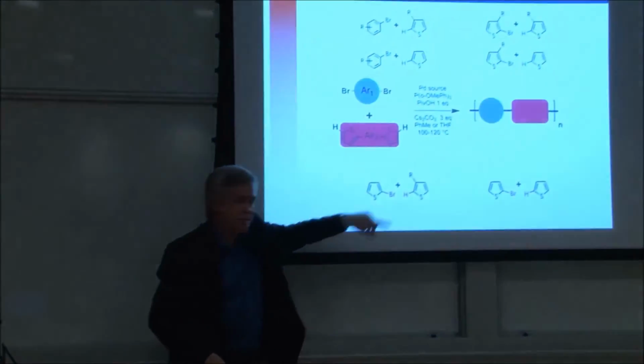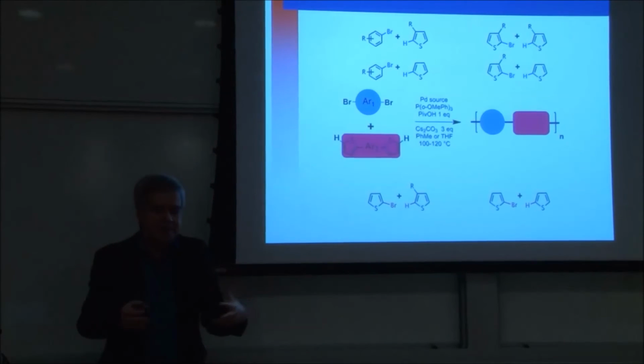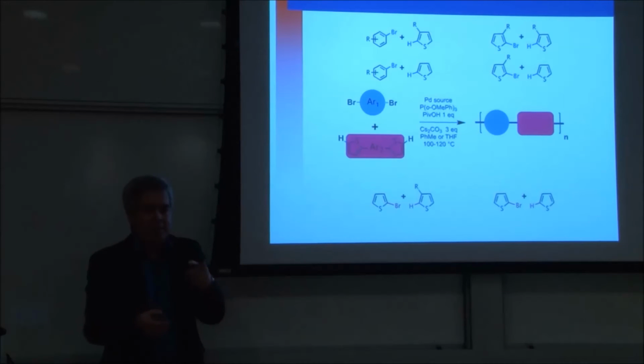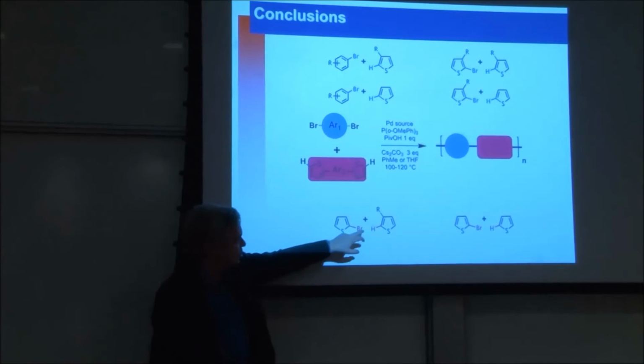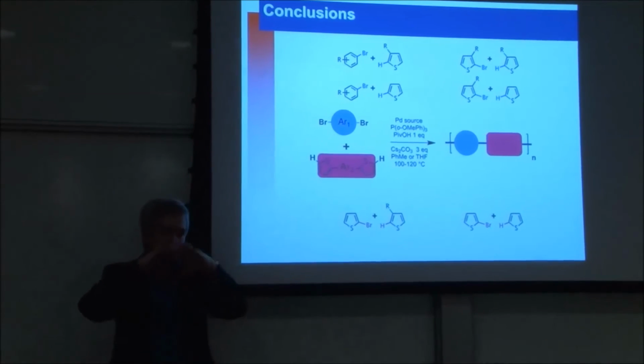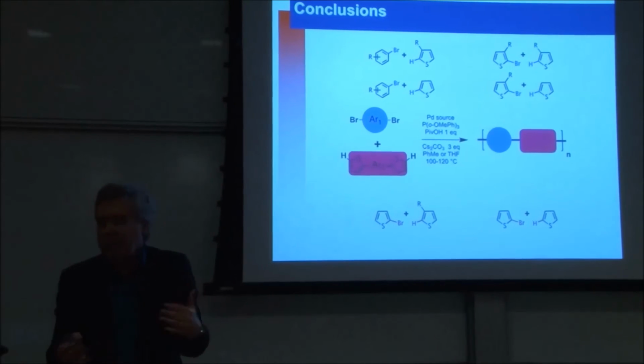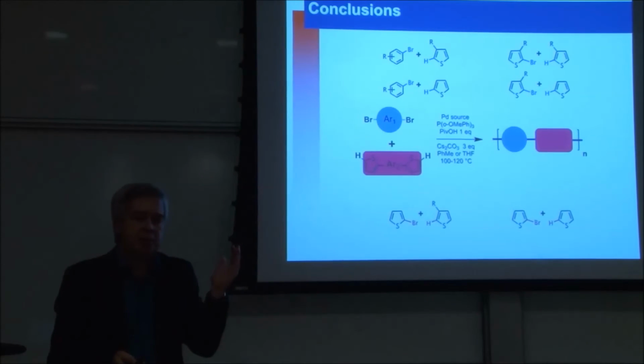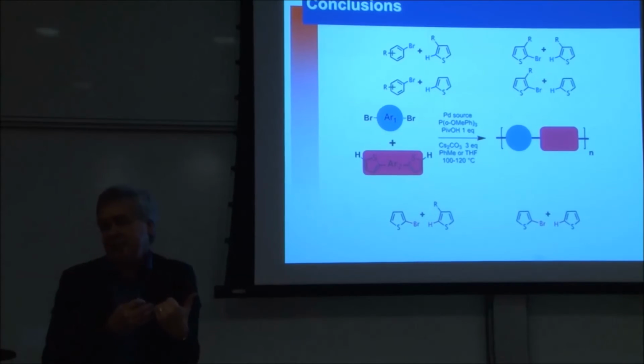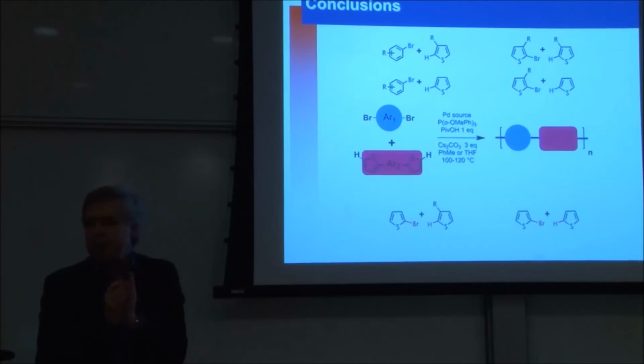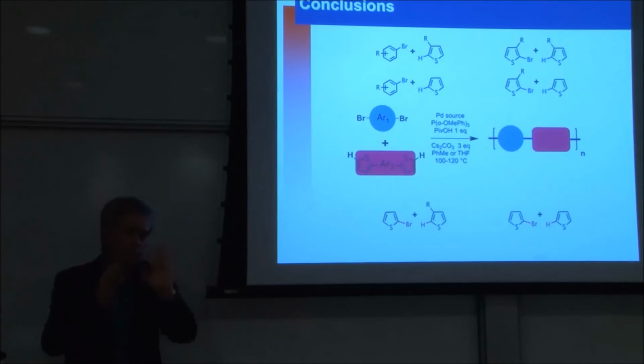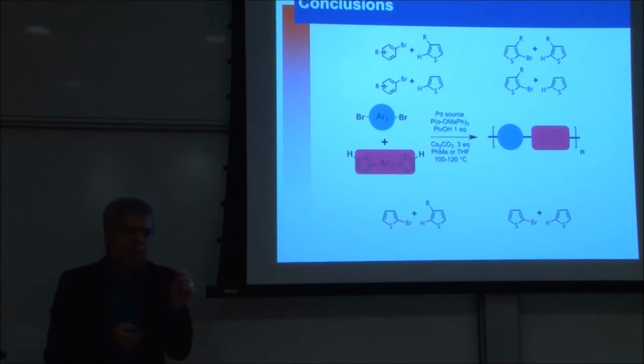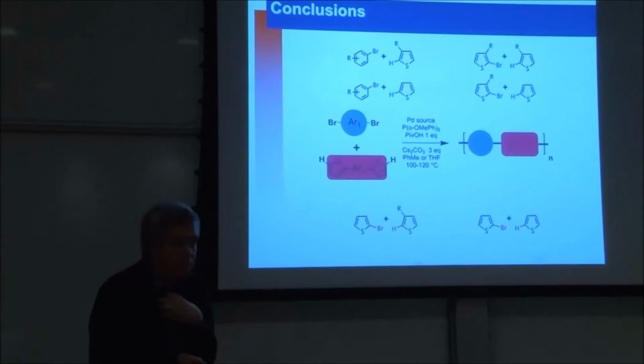My student would say that this bond is so reactive that if it doesn't see something to react with, it will make a debromination reaction. So they believe that this C-Br bond, especially when the H is surrounded by something crowded, wants to react and makes a debromination reaction. And so it's not the stability of the catalyst, it's the stability of the bromo-thiophene unit. The bromo-thiophene unit is not so stable. The bromo-aryl groups are quite stable. They will survive for many months, even in air. But the bromo-thiophenes are not so stable, and now we're not sure.